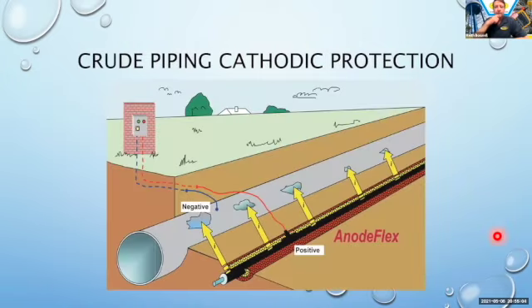At VMT, in 2018, Alyeska introduced a linear continuous anode system to help protect the crude piping within VMT. This system was installed to help supplement the existing cathodic protection systems that they had at the facility, those systems being more remote type cathodic protection systems. And through their testing and analysis, they determined that they just weren't getting enough cathodic protection out of those systems.